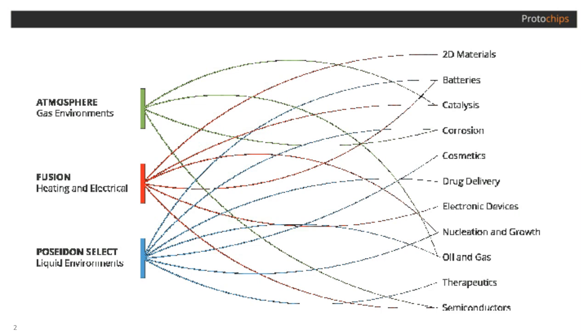One of the other products we offer is Atmosphere, which allows you to expose your samples to pressurized gases up to 1 atmosphere of pressure and up to temperatures of 1,000 degrees C. All of this is done within the safe confines of the TEM, and we find that this type of in situ research is particularly useful to the catalyst community who need to study nano-sized materials under hot, corrosive environments like those found in the catalytic converter.